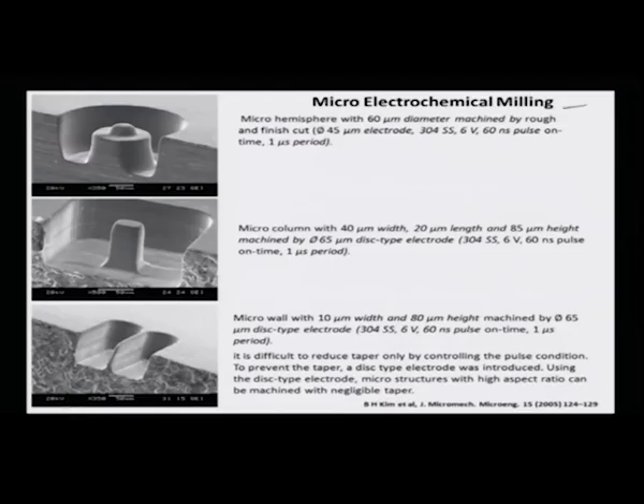You can see this is borrowed from Kim et al.'s work published in 2005, where he talks about the fabrication of a micro hemisphere with about 60 micrometer diameter, machined by rough as well as finish cuts. The electrode used here is about 45 micron diameter. It is a wire, and the electrode material is stainless steel 304, and you are basically using a 6 volt, 60 nanosecond pulse on time duration for a 1 microsecond period to achieve this particular feature right here. Beautiful again, a micro feature illustrated on stainless steel.